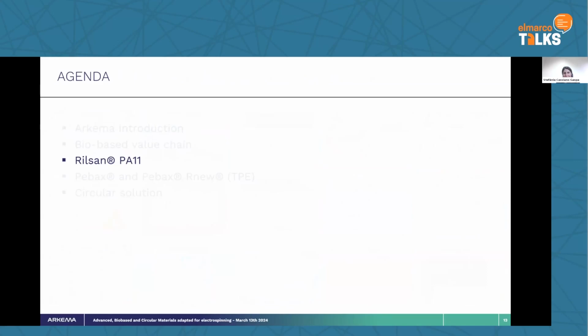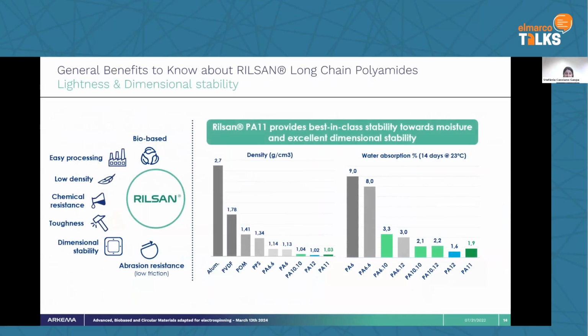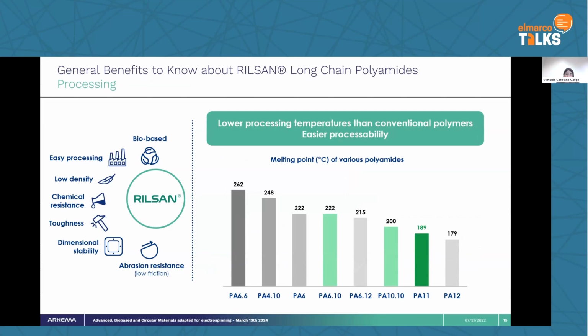Now, let's talk more about polyamide 11 and its main properties. Polyamide 11 is a long-chain polyamide. As we said, it's definitely very light. As you can see here, in terms of density, it's about 1, so lower, of course, compared to short-chain polyamides and the other materials that you can find, like PVDF, for example. As it's a long-chain polyamide, you have a very low moisture uptake. If we compare with polyester, we are in the same range. In terms of melting point, we are about 190 degrees. So this low processing temperature is also very good to save energy in some processing technologies.